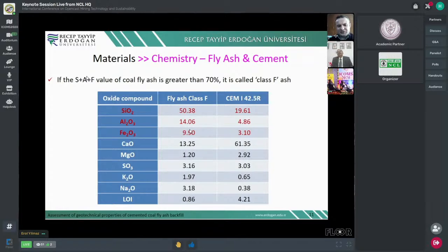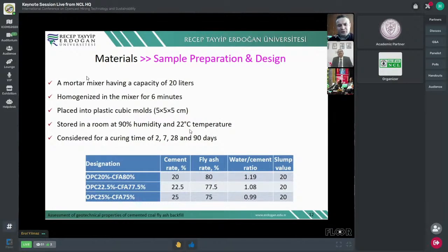And also, I want to explain how we prepare the samples and which way we follow for the design of backfill materials. So we use a 20 liter capacity mixer. We mix the coal fly ash, cement, and admixture for 6 minutes. After mixing, we place them into plastic cubic molds, 5 centimeter cubic samples. Then let them cure in a room which has 90% humidity and 22 degrees temperature, which reflects the underground conditions.